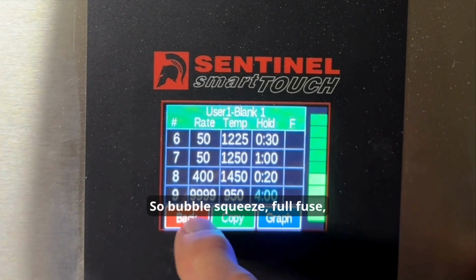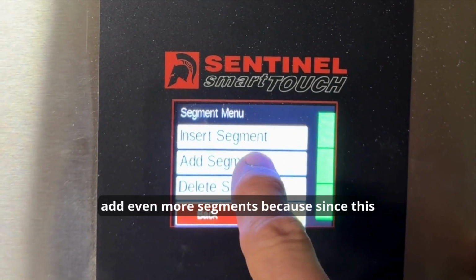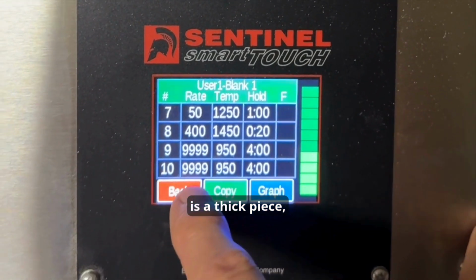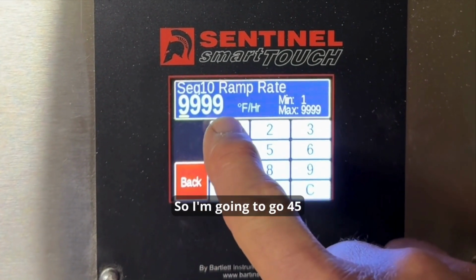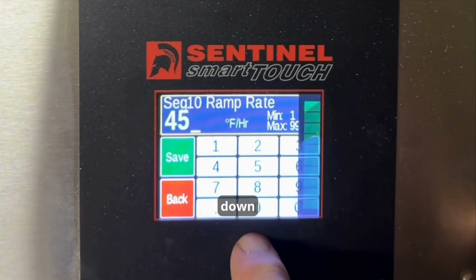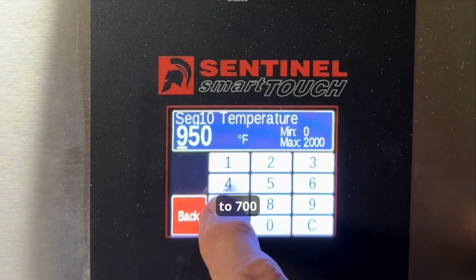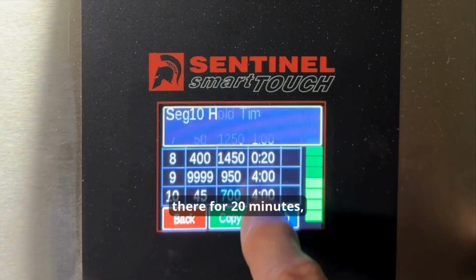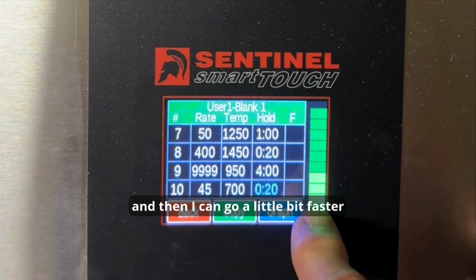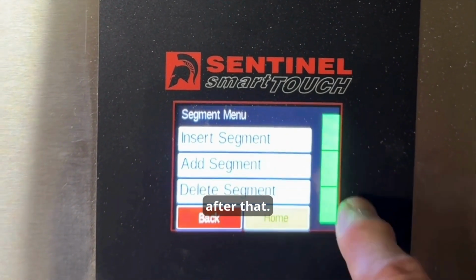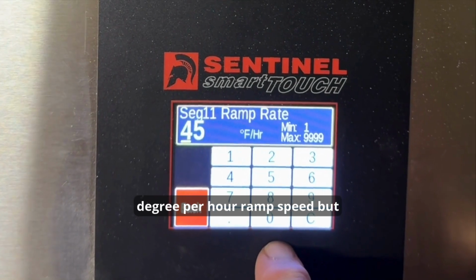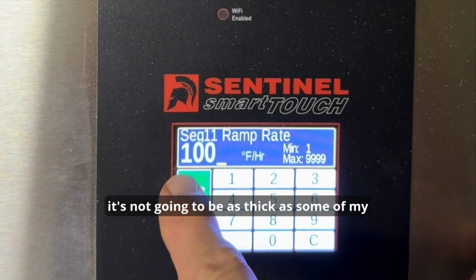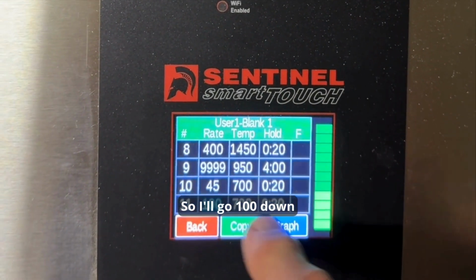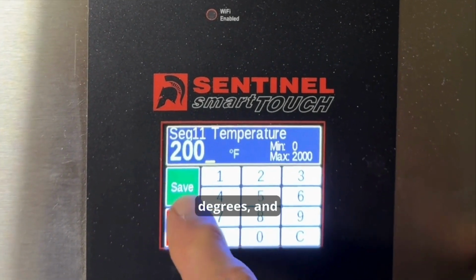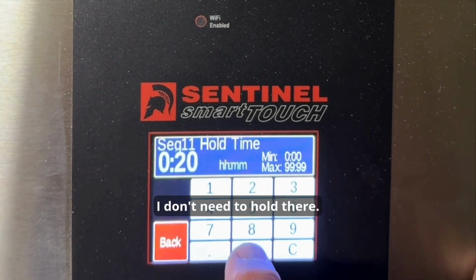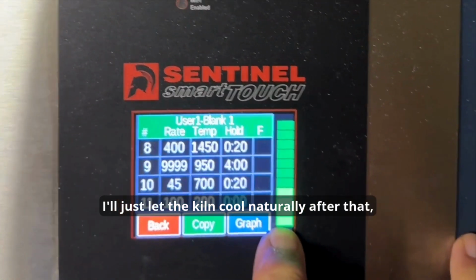So bubble squeeze, full fuse, anneal. And now I'm going to add even more segments because since this is a thick piece, I'm going to want to cool down very slowly. So I'm going to go 45 degrees per hour down to 700. And we're going to hold there for 20 minutes. And then I can go a little bit faster after that. If this was thicker, I'd probably keep that 45 degree per hour ramp speed, but it's not going to be as thick as some of my other projects. So I'll go 100 down to 200 degrees. And I don't need to hold there. And once it gets down to 200 degrees, I'll just let the kiln cool naturally after that, and we should be fine.